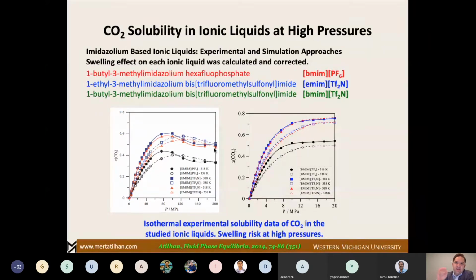Then we realized there's swelling happening here. This is what I mentioned a few minutes ago. Once the swelling happens, the volume expands. The method that we're using is the gravimetric method, so the buoyancy suddenly drops, and it registers that less and less CO2 is being absorbed. So this was a concern.